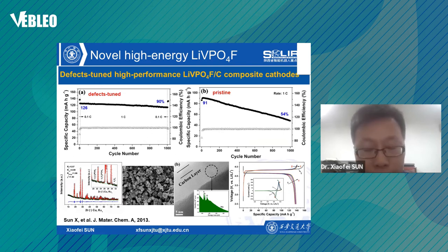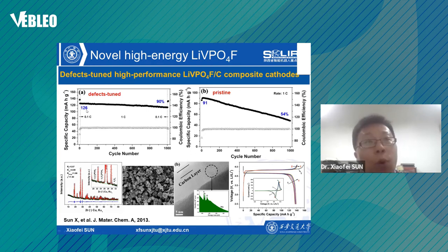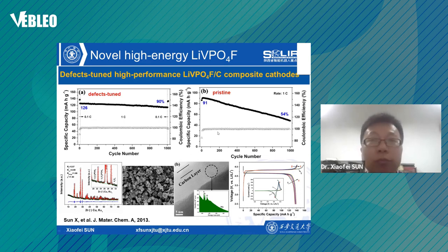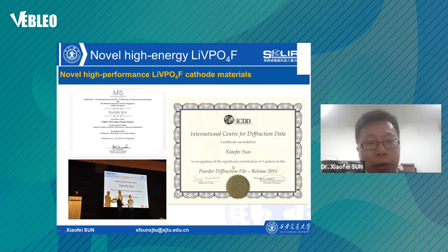These composites are beneficial for relatively enhanced performance, but the complicated synthesis process is not that favorable. Instead, we developed a high-performance composite by simply tuning the defects during the traditional carbon thermal reduction synthesis method. After rationally tuning the lithium-ion occupation, vanadium vacancies, and magnesium doping, the battery performance is tremendously improved. The discharge capacity decays slowly from 126 mAh/g to almost 114 mAh/g after 1,000 cycles at 1C rate, corresponding to a capacity retention of 90%, which means only 0.01% of the capacity is lost per cycle. The electrochemical performance is outstanding and promising for practical application, and the synthesis process is simple and compatible with traditional production lines.